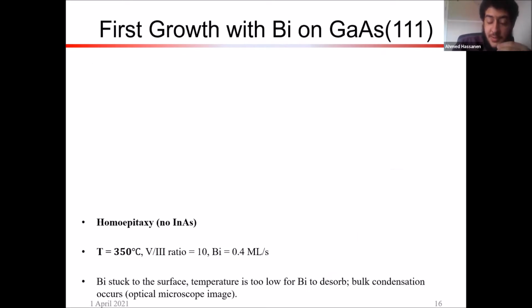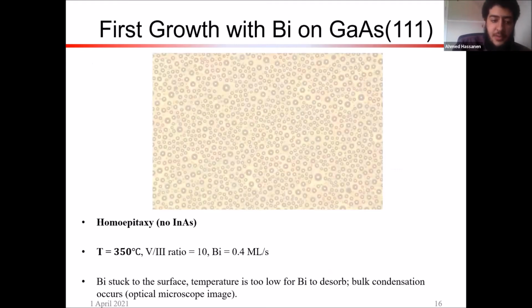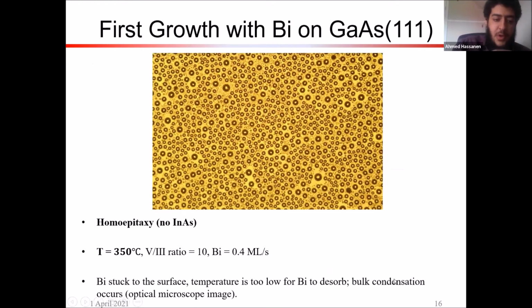So now it's time to start using bismuth on gallium arsenide 111. And so what we did was we did homoepitaxy. So we're not using indium arsenide yet. We're just seeing bismuth and gallium arsenide, just homoepitaxy, growing a gallium arsenide buffer layer and seeing how it affects the surface. So we just want to see, can we use it to create a smooth surface, for example, before we even start using indium arsenide and quantum dots.